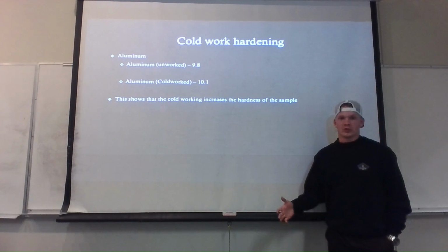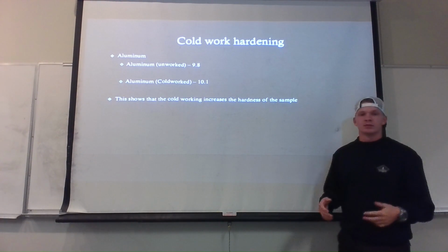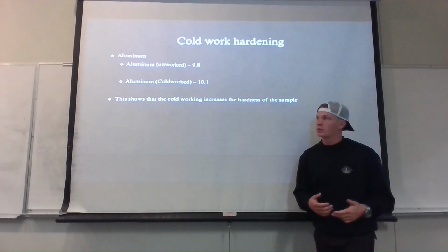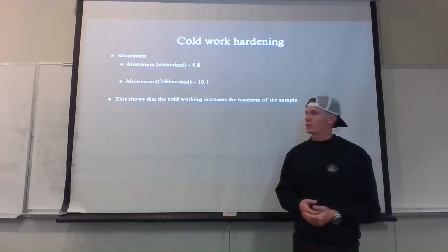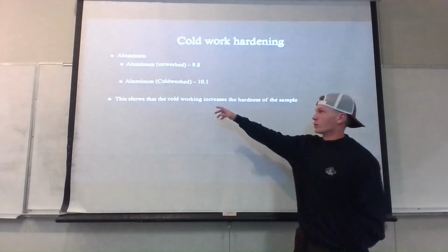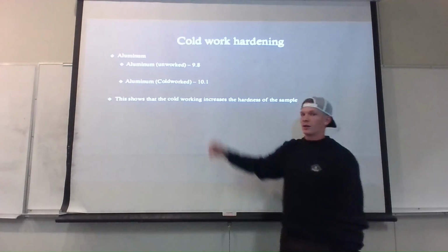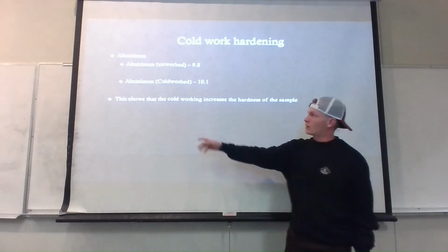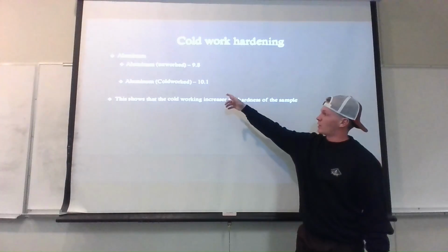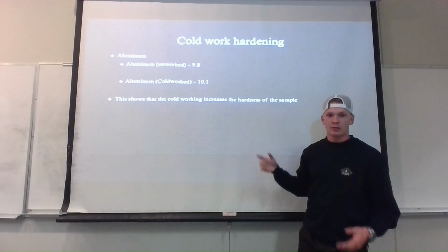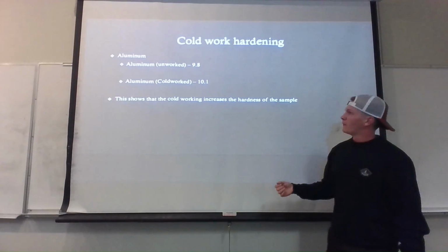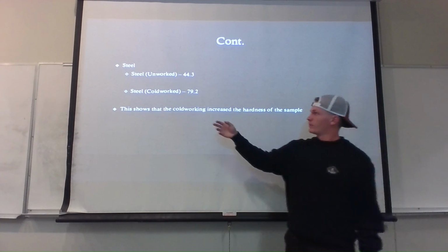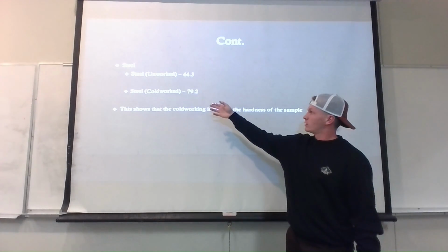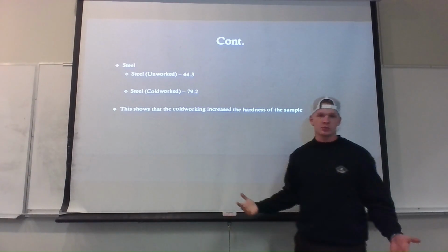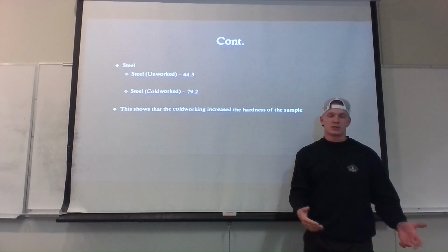So what we're looking at here is how the different samples changed when they were cold worked. So using our experiment that we did in lab, the unworked section of the aluminum had a hardness of 9.8. When we tested the cold work section, it was a hardness of 10.1. So this is showing that cold working does increase the hardness. And then same thing with steel. Unworked, it was at 44.3 hardness. And then when it's cold worked, it was 79.2. Again, this is just showing that it's going to be harder in that section where it's cold worked.